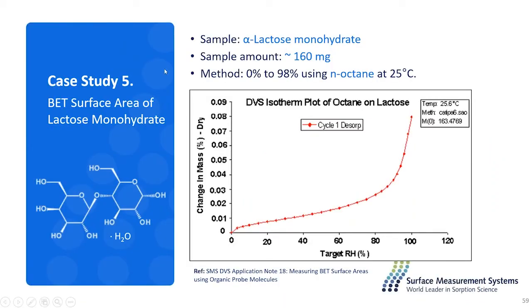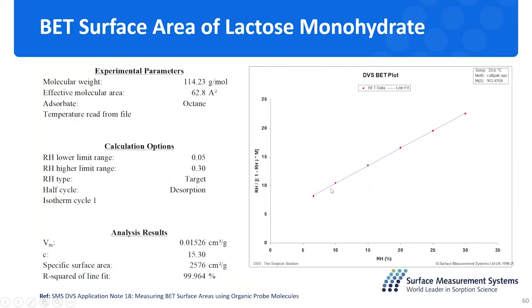The case study we have here is for lactose monohydrate. We use about 160 milligrams, using octane at 25 degrees to perform the octane isotherm. We use the points in the BET range between 0.05 to 0.30 to do the calculation with the analysis software using linear regression. Then we get the BET surface area of this lactose monohydrate of about 0.26 square meters per gram, which gave very good consistency with the literature reported value for pharmaceutical grade lactose. So DVS is capable of determining those low BET surface area materials as well as high surface area materials with 100 or 1,000 square meters per gram.